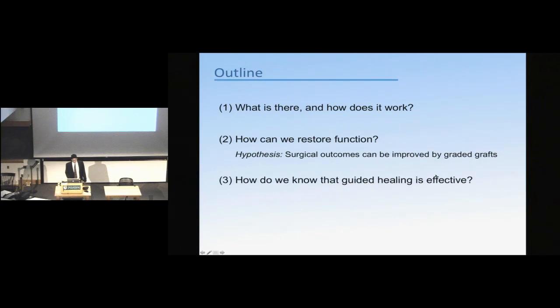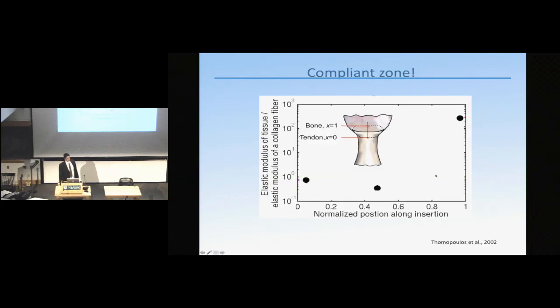So the first thing we did was just check mechanical properties. And these are very coarse data, and this is supposed to be a scale going from 0, which is tendon, to 1, which is bone. And the error bars are smaller than the markers here. So we tested a rat rotator cuff tendon to insertion site, actually this is from my colleague Steve Thomopoulos, in uniaxial tension, looked at strain fields and estimated the modulus.